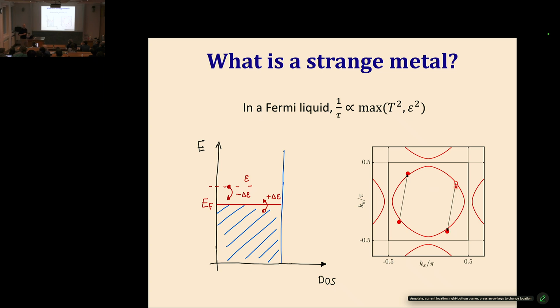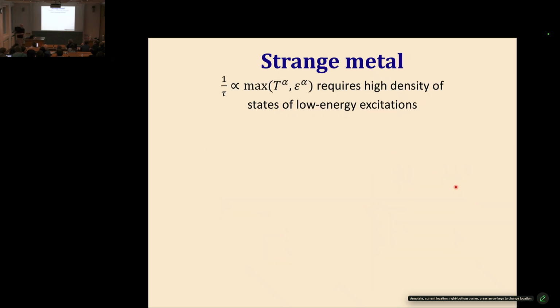Okay, other questions? All right. So what we're really after, if we want to explain strange metal behavior, assuming that at least this Fermi liquid picture is not a completely wrong starting point, meaning we still have a Fermi surface and almost well-defined quasi-particles that scatter off something, is that we need to explain the source of this anomalously strong scattering, which means that there needs to be an unusually high density of low-energy excitations in the system that would provide a parametrically faster scattering mechanism for the electrons.